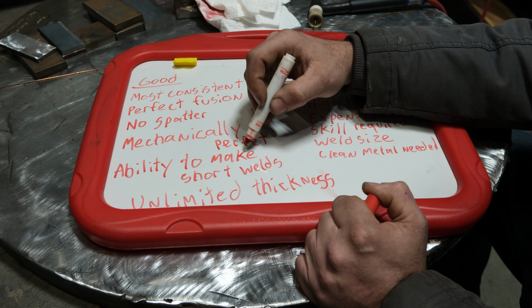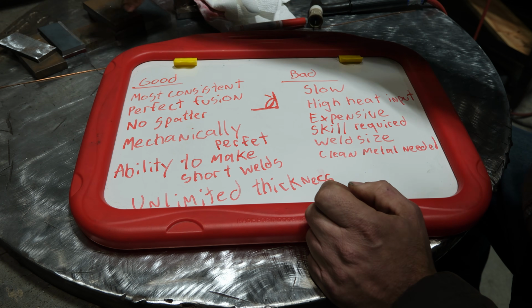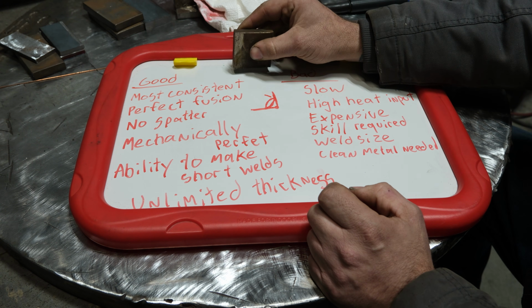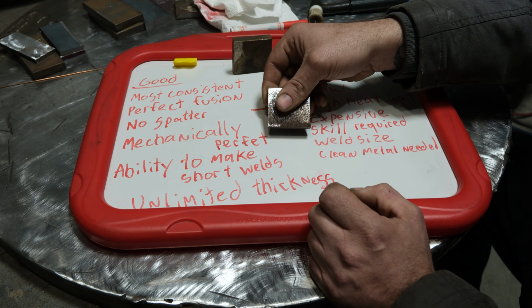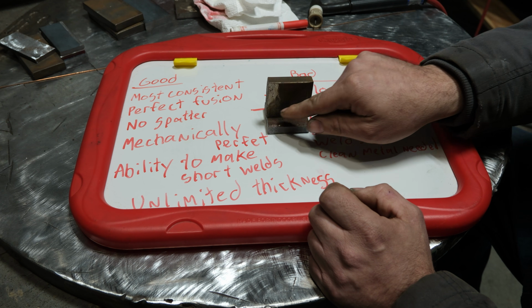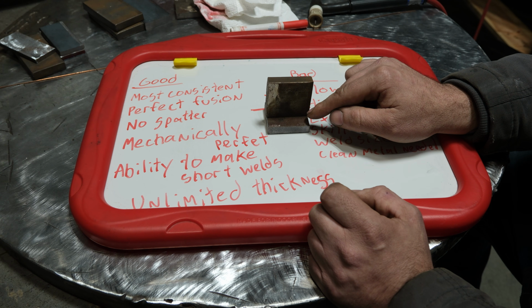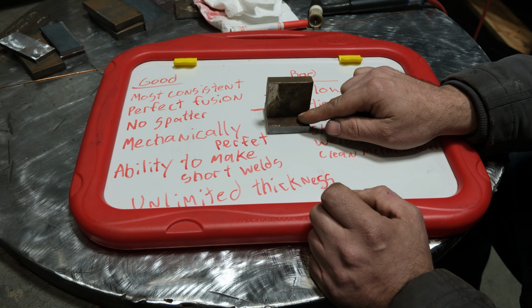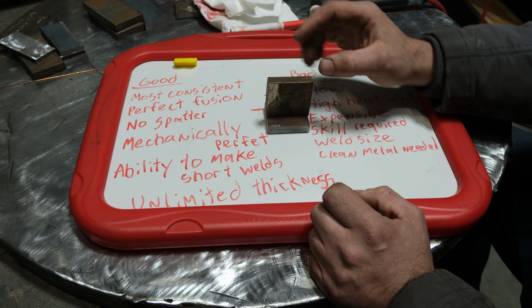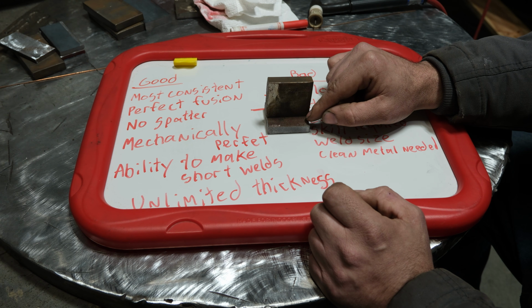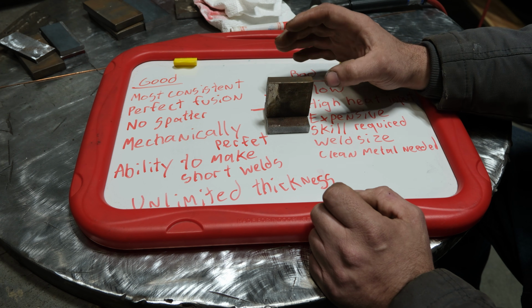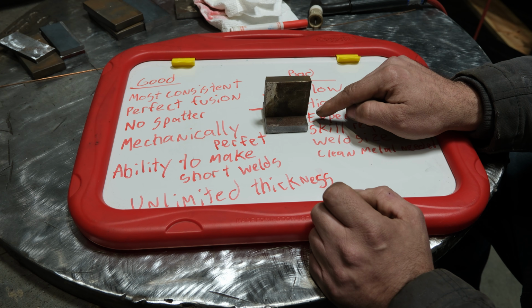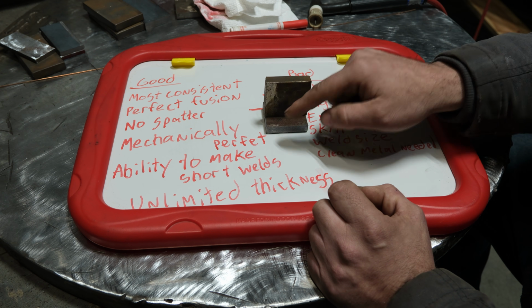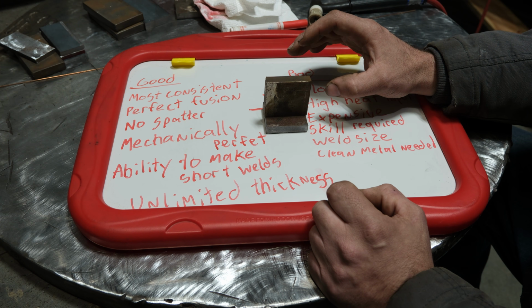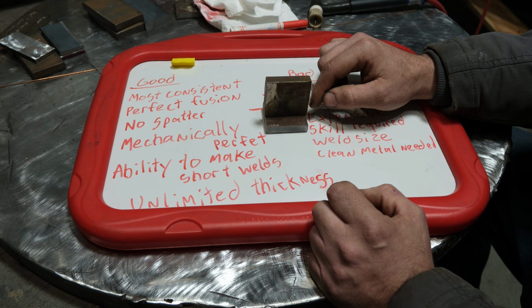Now, another great benefit is the ability to make short welds. And what I mean by that, we're going to take a piece of 1/2-inch steel here, and we're going to set up a fillet weld, and we're going to weld this short weld. Now, if you were to MIG weld this or stick weld it, what you're going to run into is about 1/4 inch into the weld, you're going to have a lack of fusion, and it exists because of that relatively cold steel, and you're just starting welding, and there's very little you can do about that. How you get rid of that is with stick and MIG, you have runoff tabs where you start welding here and then weld onto this from the runoff tab, and then that defect, that lack of fusion that exists, is cut off of what you welded.